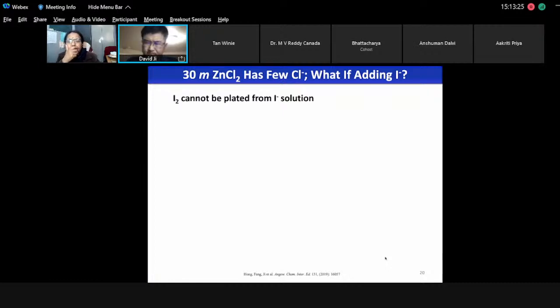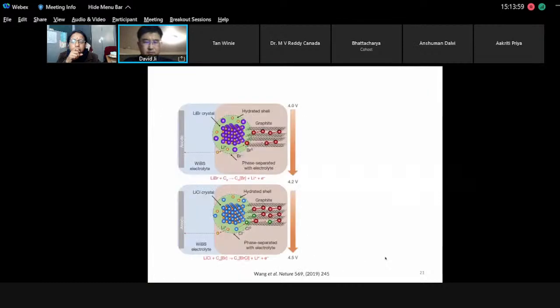It's like for lithium. A lithium insertion electrode will never have a capacity better than lithium metal, right? So it's kind of interesting to see people report capacity of silicon higher than lithium metal. That's impossible. That's impossible. So lithium metal is a plating electrode, and we hope to see whether we can plate halide.